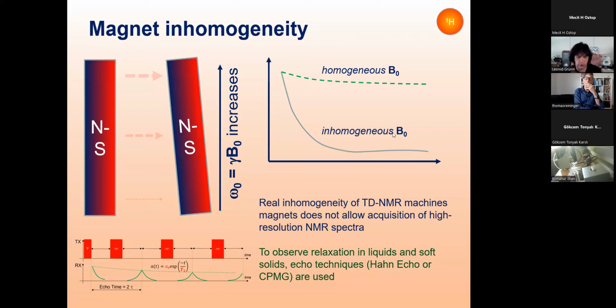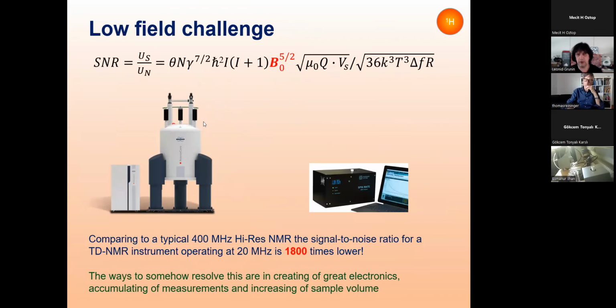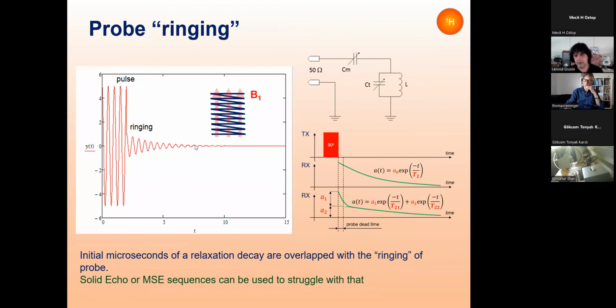And this is another interesting feature of time domain NMR. You normally work in a rather inhomogeneous field compared to big machines, and to overcome this, the classical echo sequences are used. I don't want you to learn it, but somehow we apply some pulses and we recover magnetization stroboscopically at some points, and then these points give us the envelope of the real magnetization, the real relaxation. So it's possible to overcome the inhomogeneity puzzle somehow, and the low field challenge, so the low signal. And one more problem, especially when you are dealing with solid samples, is the so-called dead time, or reading time, of the probe.